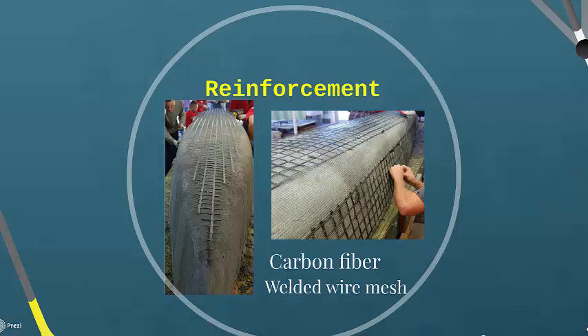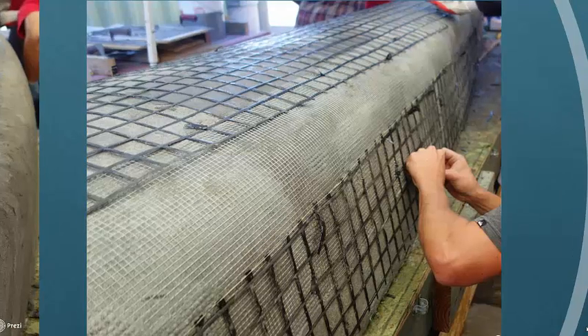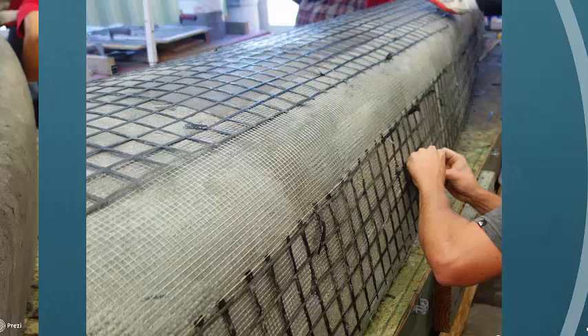The carbon fiber is the strongest of the reinforcements implemented, with 290,000 psi of tensile strength. Since the carbon fiber is much too stiff to make the curve from the bottom of the canoe to the side, the welded wire mesh was used to reinforce the areas where the carbon fiber couldn't. The carbon fiber and welded wire mesh were placed in between 2 0.1-inch concrete layers. Checking the depth of the concrete was an integral part of keeping a uniform thickness of 0.2 inches.